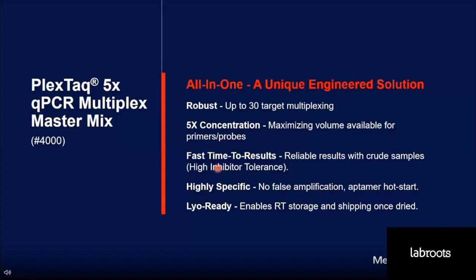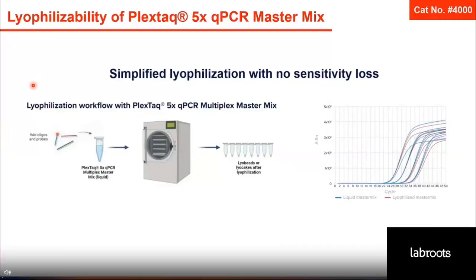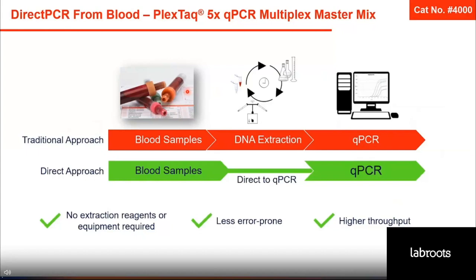And the master mix is formulated in such a form that you can lyophilize it right away. It's lyo-ready. So either you lyophilize it yourself without addition of other components, or we can lyophilize it for you. So this is an example of a simple workflow, how PlexTaq can be lyophilized for your assay of interest. So the only thing you have to do upon receiving the product, you have to add oligos and probes into the mix. Then you aliquot it, you lyophilize it, and then you can use this either lyo cakes or lyo beads after lyophilization in your assay. It is important to notice that after lyophilization, PlexTaq does not lose its sensitivity, so it performs as good as before lyophilization. So we recommend PlexTaq for diagnostic of infectious diseases because it is compatible with high concentrations of blood.